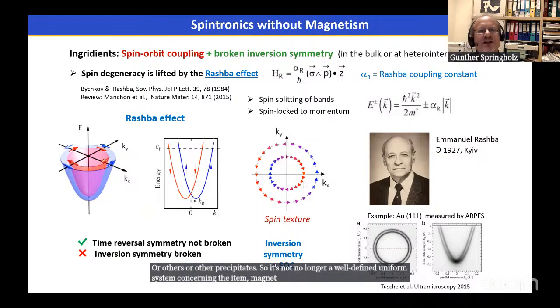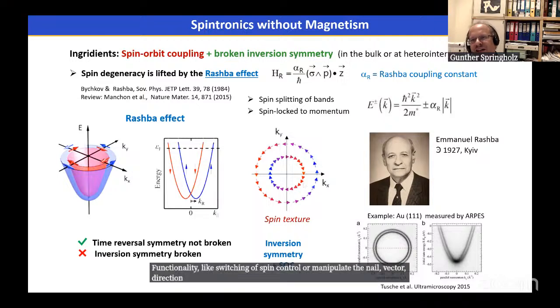Concerning altermagnets, I would like to mention one problem with altermagnets or antiferromagnets in general. For a ferromagnet, it is relatively easy to manipulate the magnetization by just applying a magnetic field, and you can reverse the magnetization from one direction to the other. Here there is the problem with antiferromagnets. The antiferromagnetic domains do not have a net magnetic moment. So if you apply a magnetic field, it is very difficult to rotate or manipulate the Néel vector. This is what you need to do to achieve a functionality like switching of spin currents, etc. If you are not able to control or manipulate the Néel vector direction, then this is difficult.